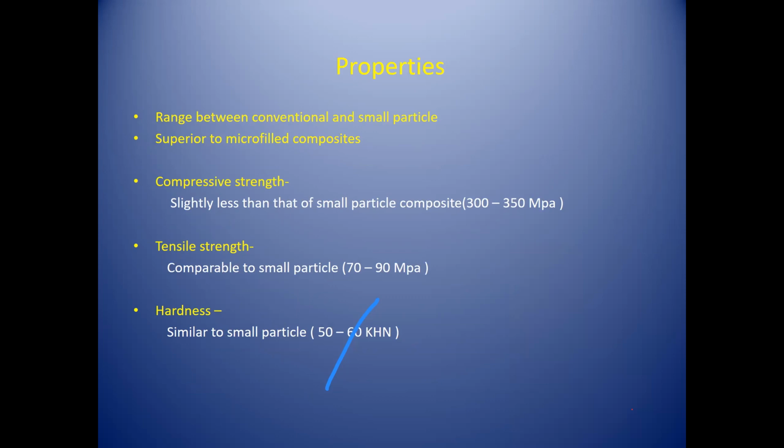Its properties range between conventional and small particle, superior to microfill composites. Compressive strength is 300 to 350 MPa, tensile strength is 70 to 90 MPa, hardness is 50 to 60 KHN.